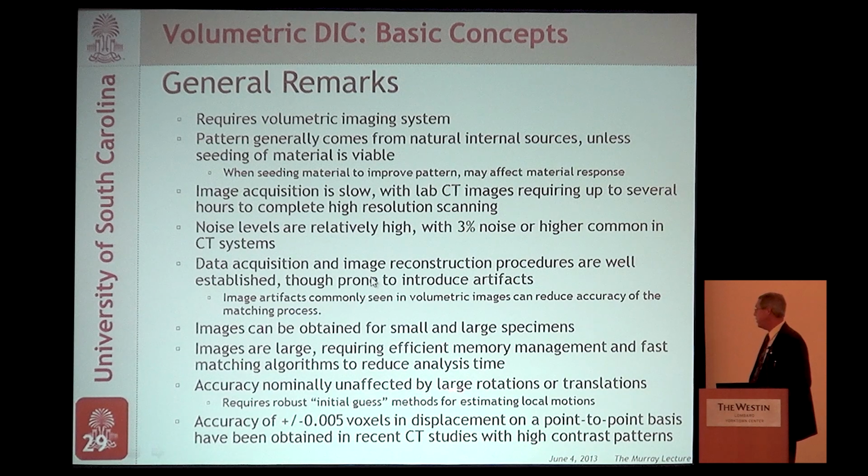The accuracy is pretty good. It's unaffected by large rotations or translations. If you have a good initial guess, then all you can do is just run through the analysis very quickly. Remarkably, we've obtained 5 thousandths of a voxel recently. So it's very, very accurate on top of this.